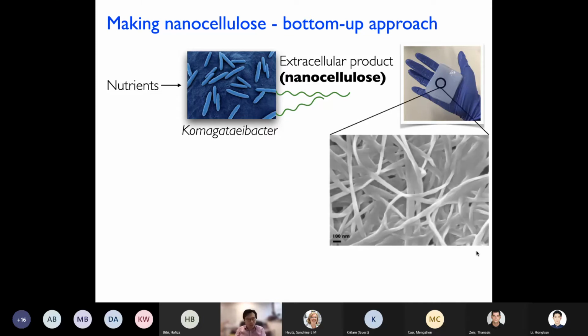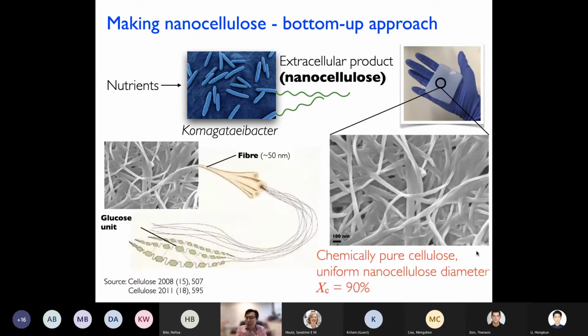If you take a closer look, it is a nanofibrous network consisting of very, very uniform 50 nanometer cellulose fibers, and this thing is chemically pure, 100% pure cellulose. The cellulose microfibrils, again nanocellulose derived from wood, are not chemically pure. They typically contain what we call hemicellulose. Bacterial cellulose here is actually pure cellulose without any other impurities.